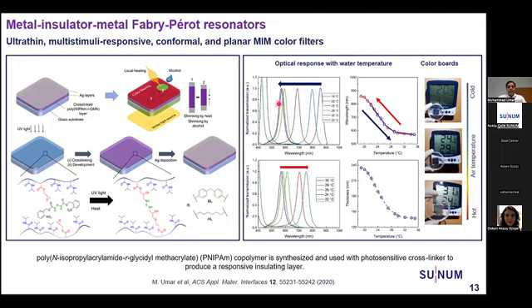If we put the sample in the water, initially at room temperature this polymer swells, which means it absorbs water from the environment. Then when we increase the water temperature, it retracts the water from inside, and the size of the cavity starts shrinking. So the resonance spectrum goes to a lower wavelength.